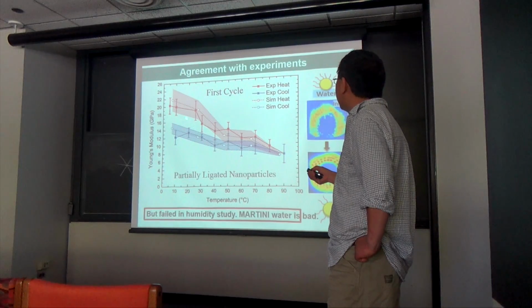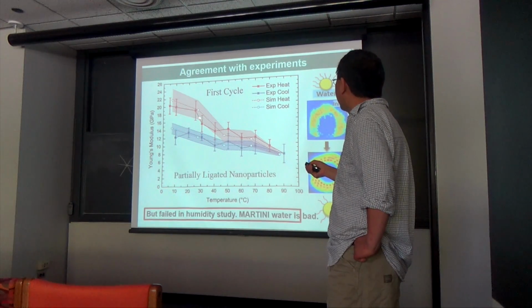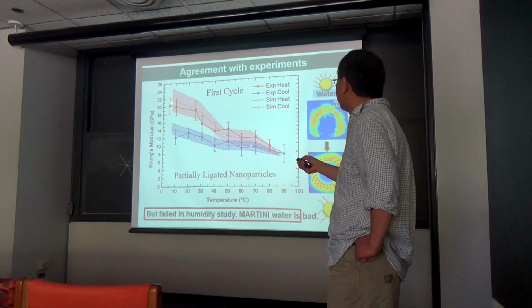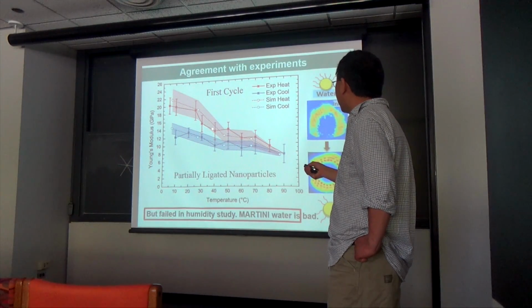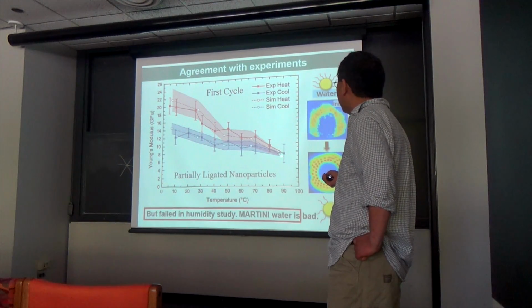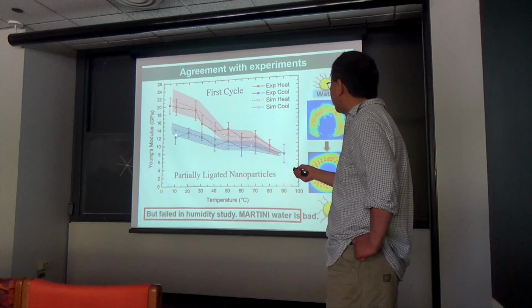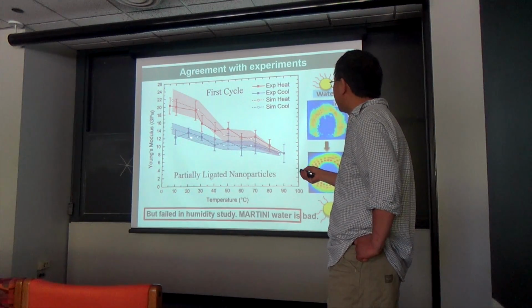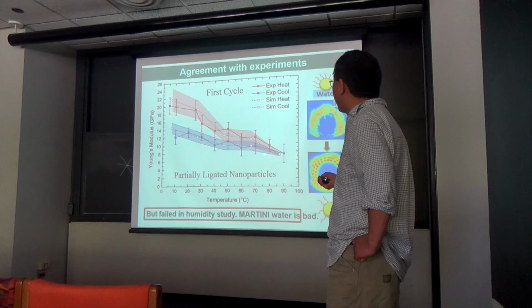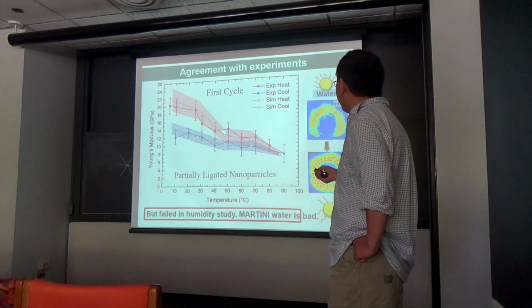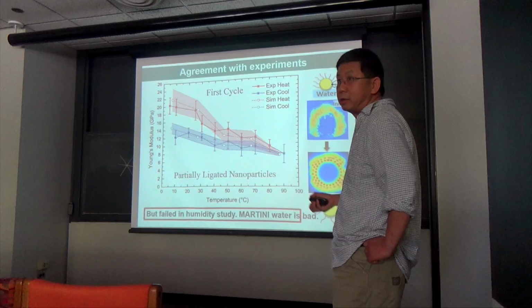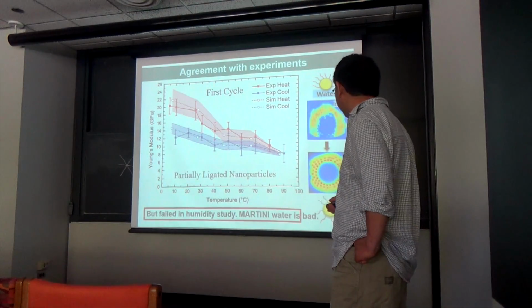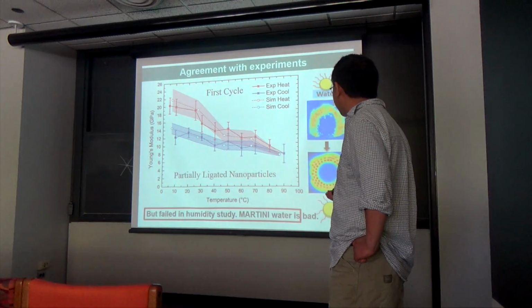properties. So for instance, this is experimental data that shows that the Young's modulus at a high temperature gradually decreases, and then when you come back in temperature, it has a hysteretic behavior. But what it really is associated with is the ligand distributions around the nanoparticles. And so this we can capture with simulations.